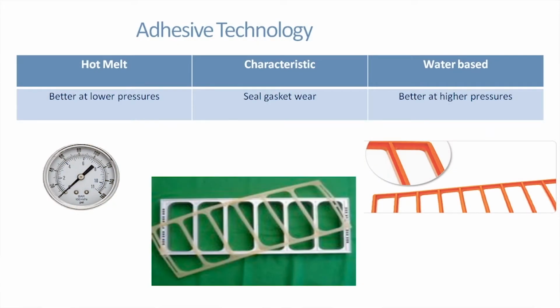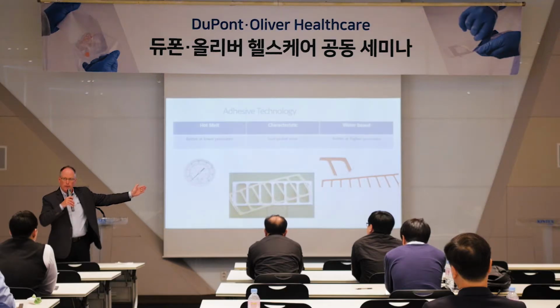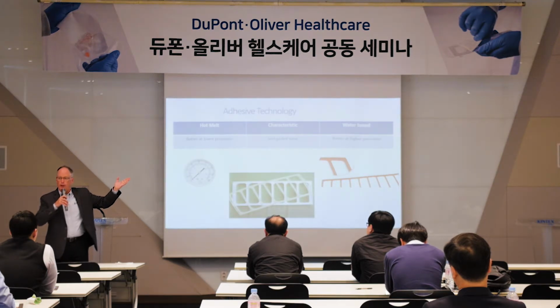One other characteristic, seal gasket wear. If you think about a sealing process, you've got rubber gaskets that are part of that process. One difference is that with the hot melt, you usually need less pressure in your process to get a good seal, and I'm going to talk about that more later. With water-based, they typically work better at higher pressure. So you'll get a little bit more wear with your seal gaskets when you're using a water-based system, so you just have to think about that during your PMs, your preventative maintenance procedures.